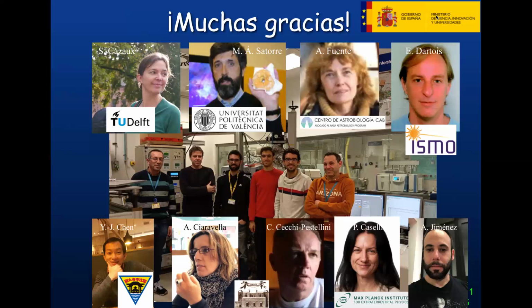And now we are working on a paper where we extrapolate this temperature measured in the lab to the astrophysical temperature. Because if you talk to an astronomer, he will tell you that water ice is not formed at 170 K, but at 110 K. And you arrive at this value if you extrapolate the vacuum level in the lab to the real vacuum in the interstellar medium, which is still 2 orders of magnitude better vacuum. So about 2 orders, compared to the ultra high vacuum. It's still 2 orders in a dense cloud.